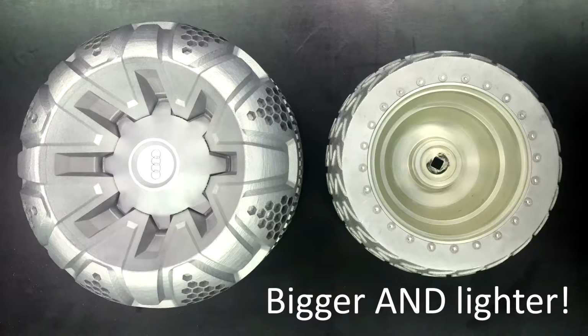The cool thing is that our new rover is actually a little bit bigger again. We started with a very small one, and we figured out that it's too small. We increased it a bit, and it's too small again. The last size increase came in the form of the wheels, because we found out that with more surface we can climb higher slopes, and decreasing the weight was also very helpful. The wheel you see on the left-hand side is new, and it's 200 grams lighter despite being bigger. We were able to do that because the left one is fully 3D printed. And this is pretty darn cool.